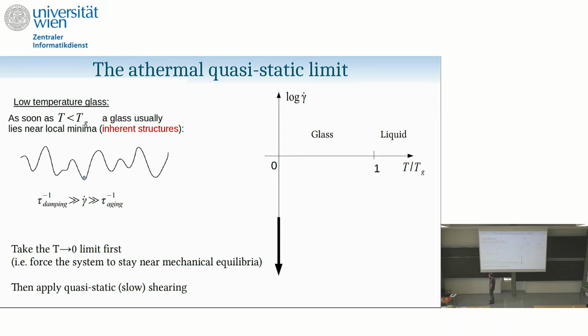Right? So the idea is, okay, let's take first the limit of very low temperature. And it's relevant because when you are below 80% of Tg or 50% of Tg, the alpha relaxation time is up in the sky. And so the thermal relaxation, I'll come back to that, a priori doesn't matter at all. So you can just first take the T to 0 limit. And taking the T to 0 limit means just bringing the system to mechanical equilibrium. And then what happens? Well, nothing. You can wait and wait and wait. If you extrapolate the alpha relaxation time for a glass, it's beyond the age of the universe. So you can really wait for a very long time.